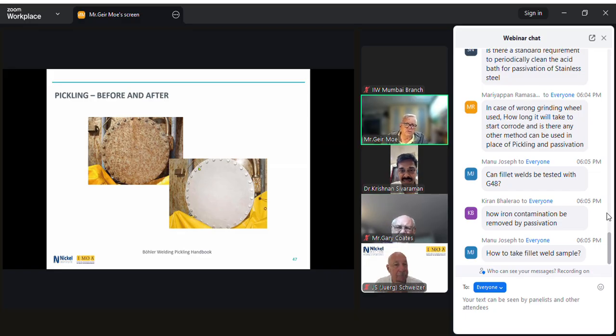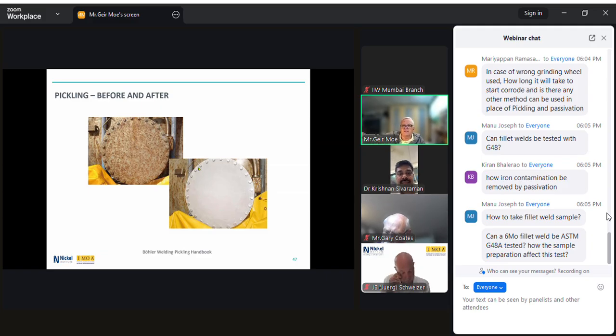What are the causes of pitting after the pickling process near weld joints? Well, I'm not sure what they mean by near weld joints. If you've done the pickling properly, you've removed the heat tint and the chromium depleted layer. If you've got pitting now in the weld area, it would primarily be because of roughness. The surface of a weld is rougher than the original base material, and as we saw in one of the charts, a rougher surface is less resistant to pitting than a smoother surface. That's the only reason I could think of why you might still be getting pitting. If the balance of the material is fine and it's just pitting in the weld area, it's probably just surface roughness.